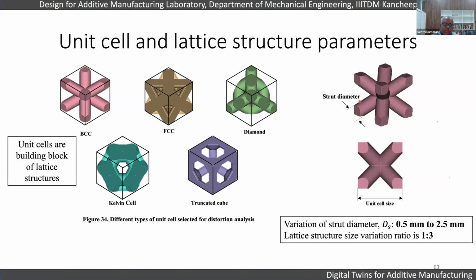Here we used different types of unit cells. First, we wanted to understand the size effect. So we varied the strut diameter from 0.5 to 2.5 mm. We tried to maintain the lattice structure shape by maintaining a 1:3 ratio in the size variations. First we studied the size variations, and then we studied the shape variations.